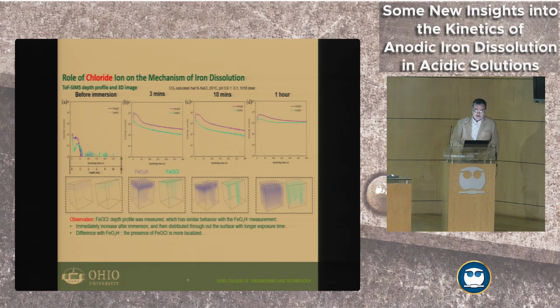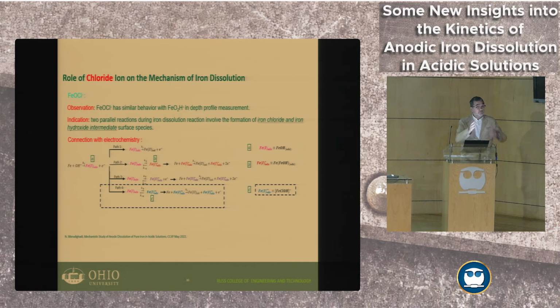And I think she puts it all together to see here, combines it with hydroxide. So essentially you have hydroxide and chloride simultaneously developing, but sort of independently. Where you have hydroxide, you don't have chloride, and where you have chloride, you don't have hydroxide, but both of them cover different areas. Well, it depends on the pH. If the pH is low, you don't have much hydroxide, so that pathway is hard. And vice versa, if the pH is high, then you have a lot of hydroxide and that pathway is easy. Same with chlorides.